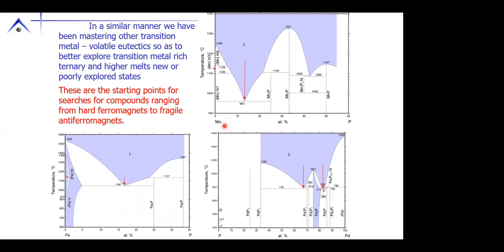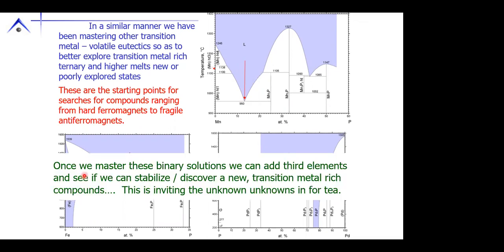Okay, here's a manganese phosphorus eutectic at about 10% phosphorus. We came up with ways of creating a liquid that does not have large vapor pressure above it and then allows us to try to grow new ternaries. Okay, so what we can do is once we master these binary solutions, we can add third elements and see if we can stabilize or discover new transition metal rich compounds. It's really like inviting the unknown unknowns in for tea.